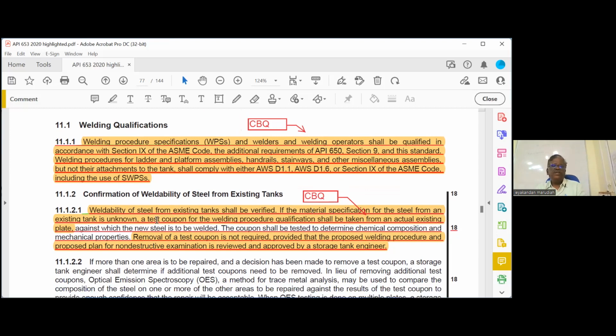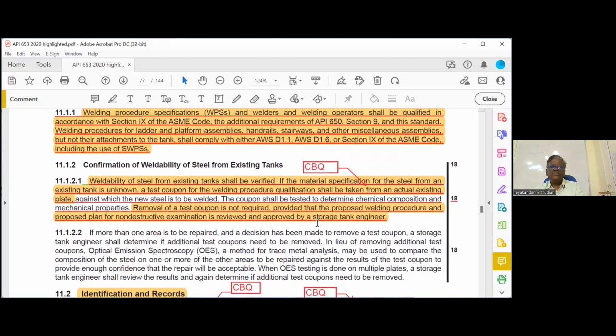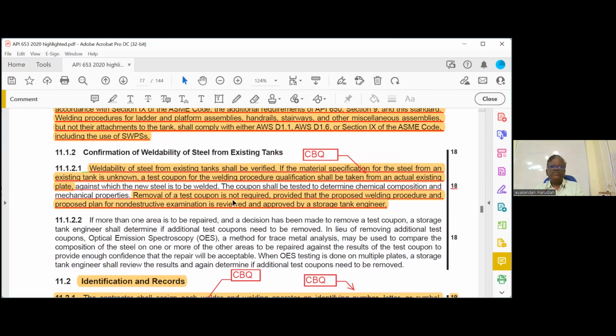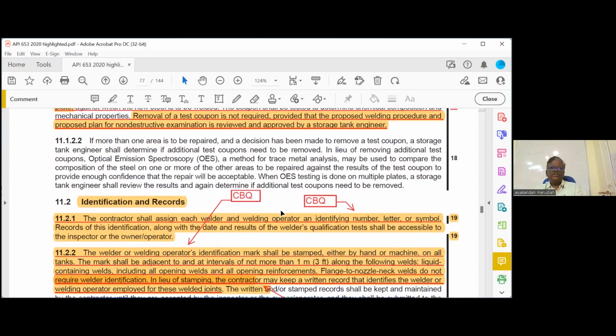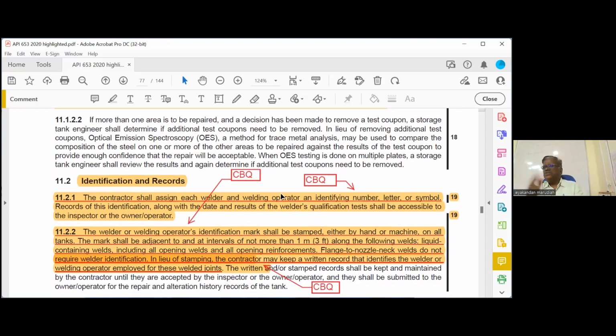Then confirmation: weldability of steel from an existing tank shall be verified. If the material specification for steel from an existing tank is unknown, a test coupon for the welding procedure shall be taken from an actual existing tank. Suppose you don't know the material weldability, you have to take a coupon cut. Then highlight the next line. Removal of test coupon is not required, provided that the proposed welding procedure and the proposed plan for nondestructive examination are reviewed and approved by the storage tank engineer. Then these are almost 650 requirements only.